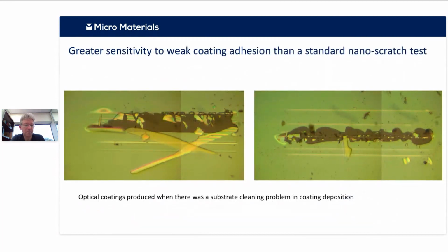So here's just a very simple example. In this case, this is for optical coatings that were produced on a transparent substrate, when there was a problem in the coating deposition where the plasma pre-cleaning wasn't working effectively. And in this case, you can see clearly that there's a big adhesion problem, and the random scratch test, or the statistically distributed scratch test, has picked that up quite nicely there. So you're getting complete removal of these areas in the test, which is a much more effective way of doing this than a standard nano scratch test.